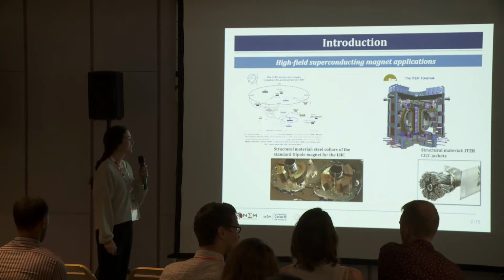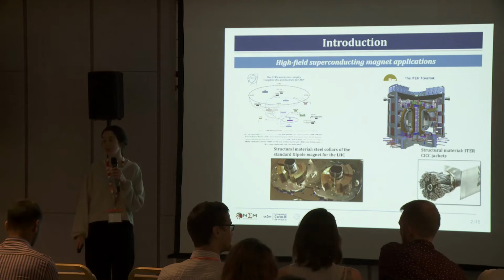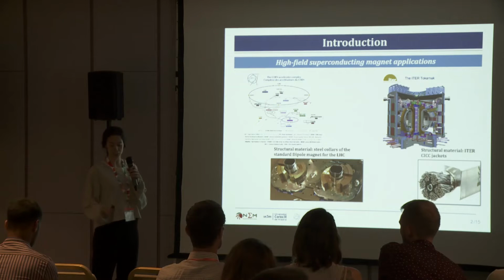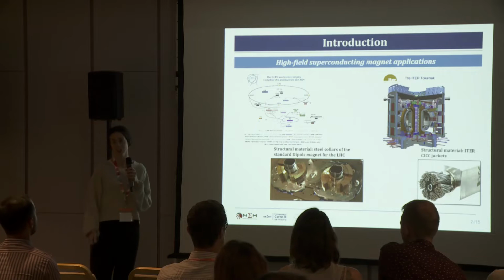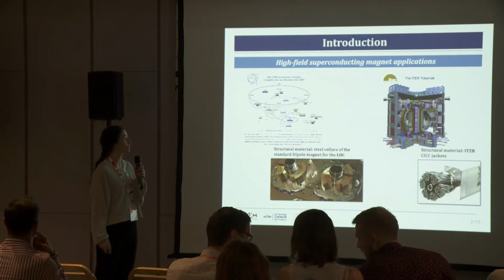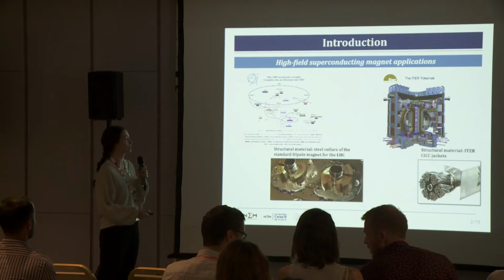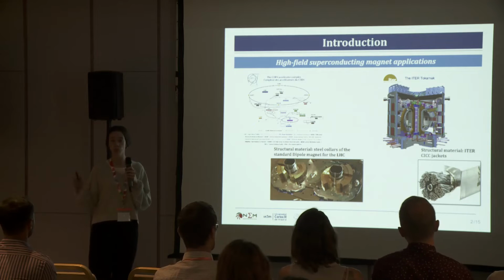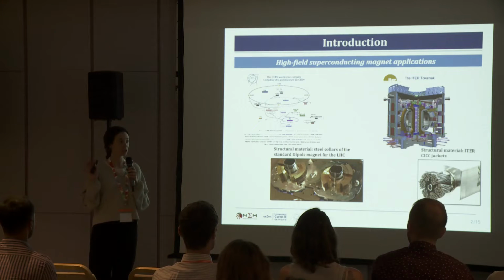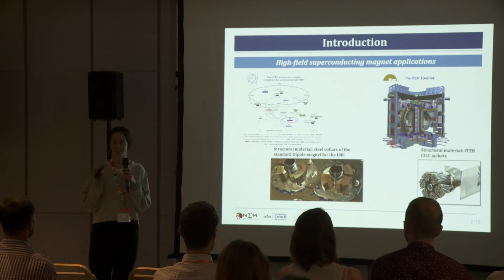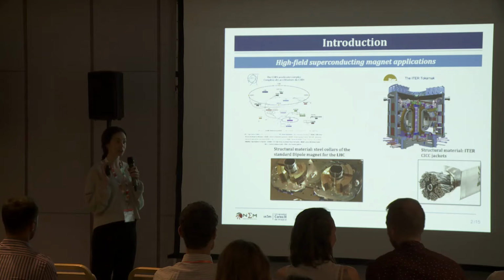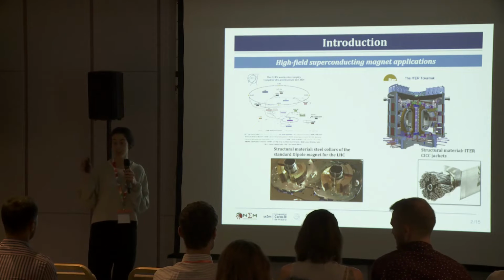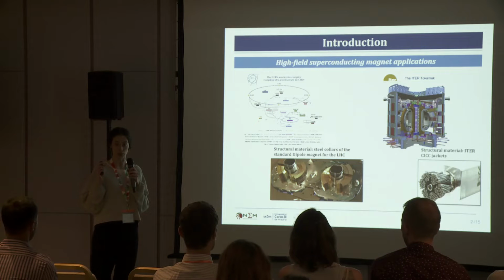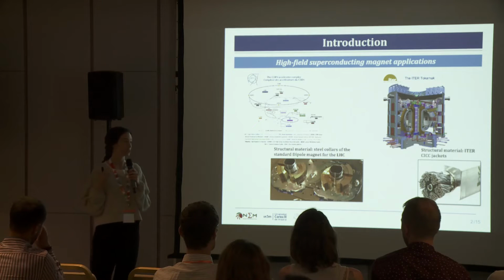So this kind of study is important, is interesting for applications that use high field superconducting magnet systems. This is the case, for example, of the LHC at CERN, for sure, and also, for example, the fusion reactor system for ITER. So in both cases, they need to cool down the magnetic system to cryogenic temperatures in order to have the superconducting state. The problem is that these cryogenic temperatures are affecting not only the magnet system, but also all the structural materials that you need to place around in order to counteract the strong magnetic forces. And this structural material is made of austenitic stainless steel. That's why it's important to study the mechanical behavior, and in particular the fracture behavior of austenitic stainless steel.